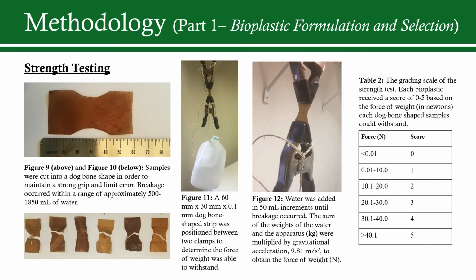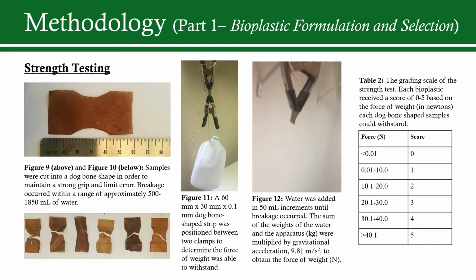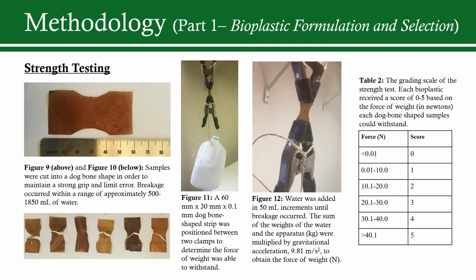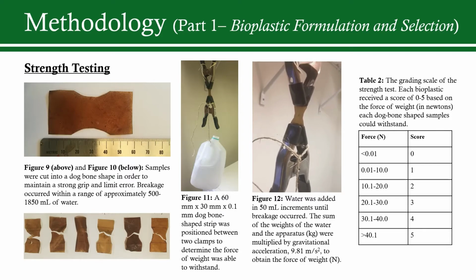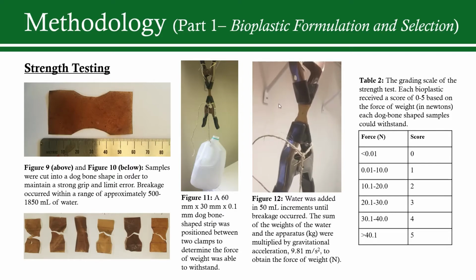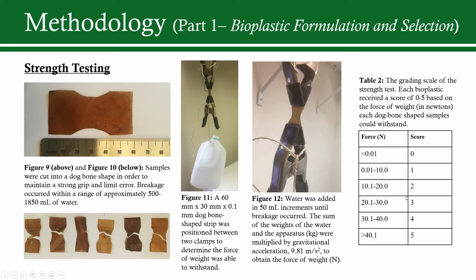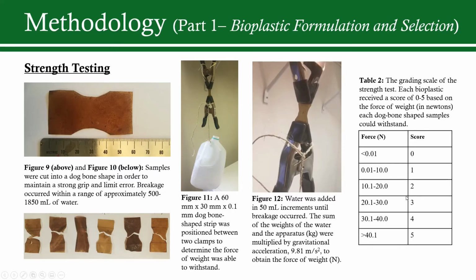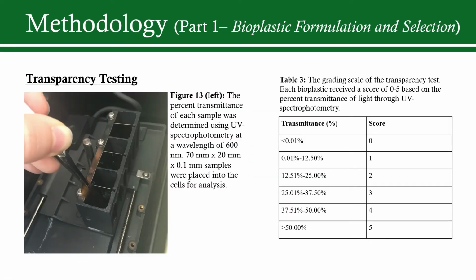So to determine strength, first, the samples were cut into dog bone shapes. An apparatus was devised to test the amount of weight a film sample could withstand before breaking. The scale on the right here shows the ranges of force in newtons that correspond to each point value. Next, UV spectrophotometry at 600 nanometers was used to determine percent transmittance, or transparency, of each film. Here's the grading scale that I used for this test.